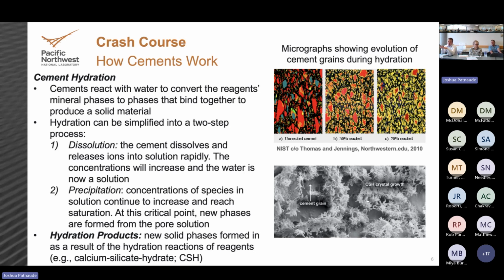One thing to take away from this slide is that regardless of the application, whether it's a sidewalk at your house or another cementitious material, once they get to that hardened, cured state, they're not done reacting because you do have those unreacted grains that sit there. So cements are a dynamic system that continually react at a very, very slow rate, but over time they continue to evolve. Depending on how you engineer your material and what environment it's placed into, those continued reactions can lead to processes that could fail if you're not smart about where you're putting it, or, like most of the cement industry does, material can get better and better with time. And the perfect example of that is the Roman concretes.